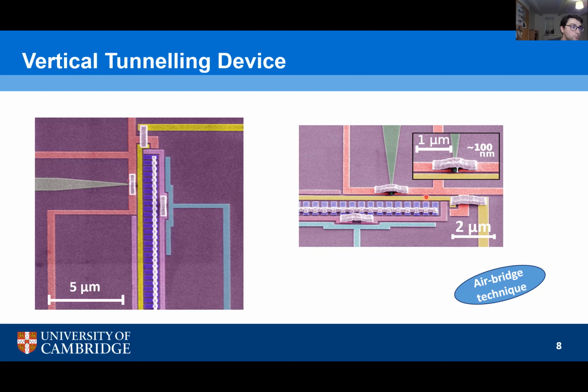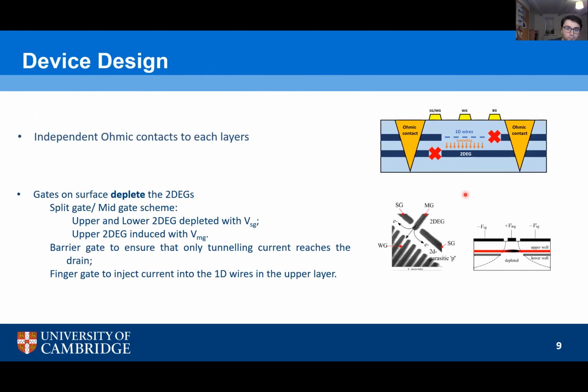So it's essentially 2 E-beam stages. First one for the surface gates, second one for the air bridges. And then, to create the 1D wires, what you do is you squeeze the channels and you can vary that to play with how strong the interactions are.